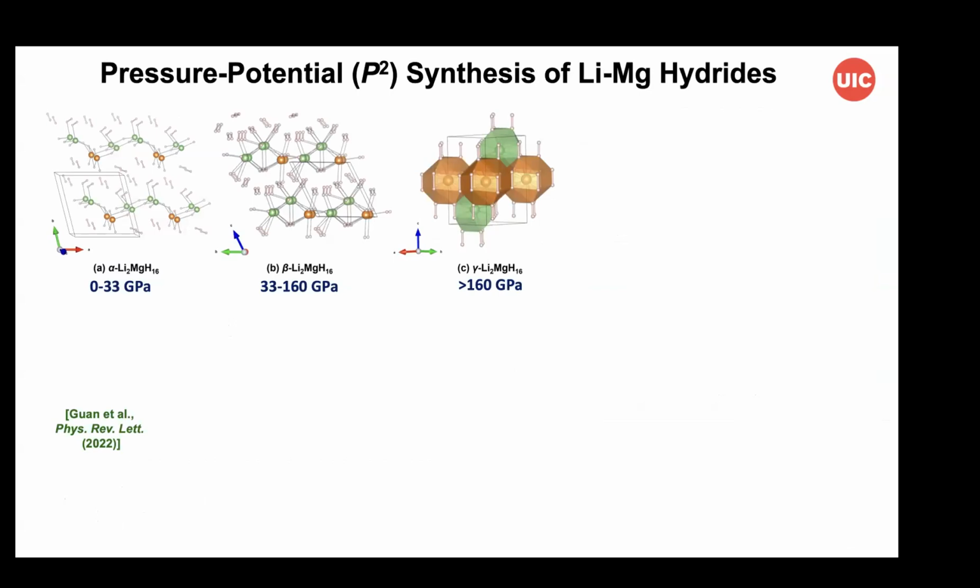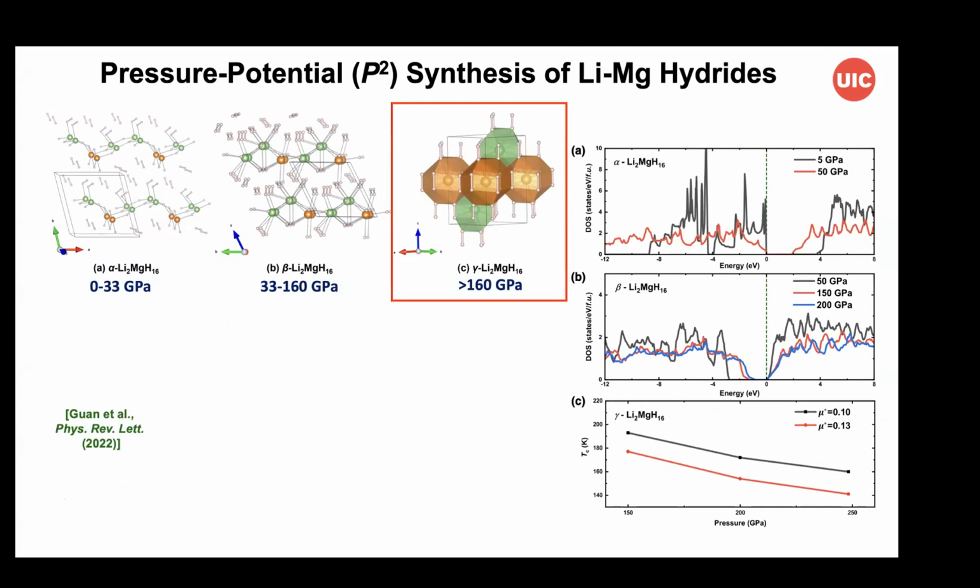And in some more recent work that was published this year, looking at the lithium magnesium hydrogen system, in collaboration with the Jilin University group, returning to the Li-Mg-H system, looking at these phases plus the higher pressure phase with the very high Tc, applying the same sort of methods. One finds that the first two structures, these were not actually reported in detail in the original paper that they published, are insulators, but this one here, the gamma phase, is stable above 160 GPa in the absence of any kind of electrical potential.